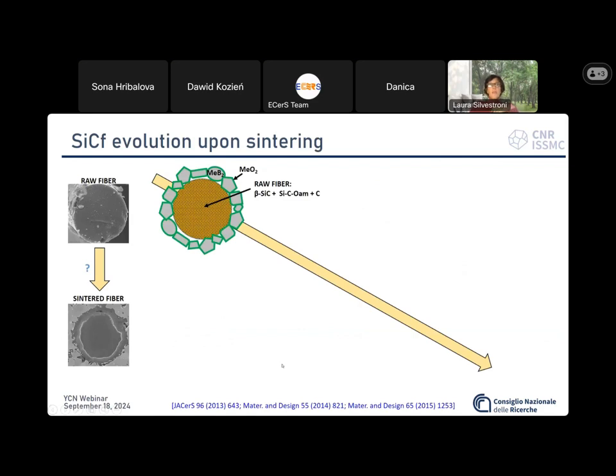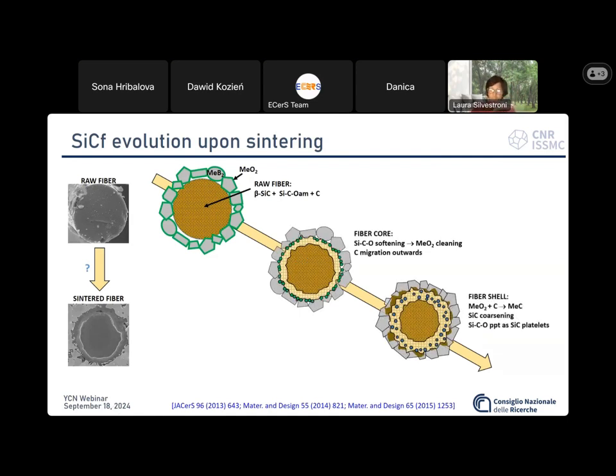So the path from the raw fiber to the fiber in the sintered composite passes through some fundamental phenomena that derive from the fiber composition. For example, in the case of silicon carbide, it includes silicon oxycarbide softening, which is included in the raw fiber, carbon migration outwards, silicon carbide crystallite coarsening, and then we have, of course, cleaning of the oxide particles and formation of silicon carbide platelets well anchored to the matrix.